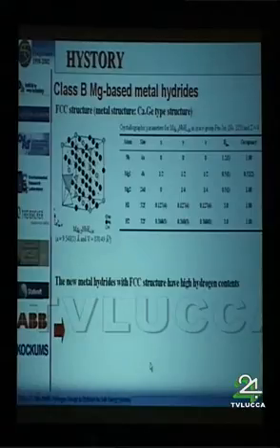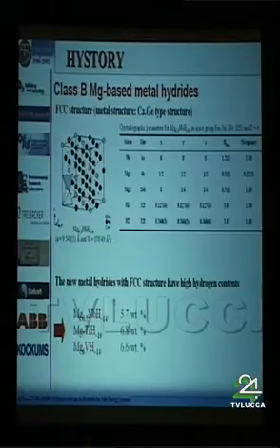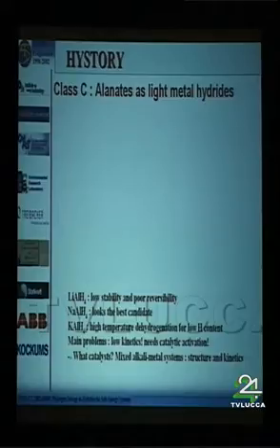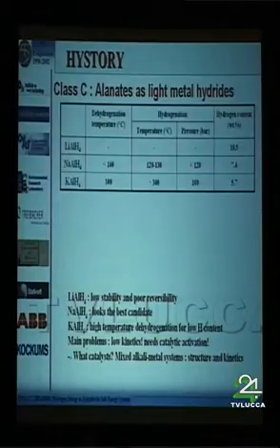And these materials exhibit very nice hydrogen uptake, but unfortunately these materials are not stable. If you completely desorb this type of alloy, this type of ternary hydride, the alloy is not stable. But it should be interesting now to consider that this type of material, which is very metastable, should be one of the active parts of the interface between niobium, titanium, and vanadium, considered as a catalyst, onto the magnesium grain. So effectively, the third class of material we consider is alanates, light metal hydride.